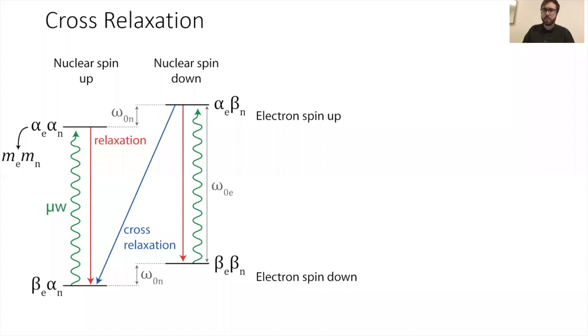All right. And then next on the list, when you mentioned that your microwave power, you don't have enough to fully reduce that Knight shift, if you extrapolate out, how much power do you think you would need to reduce it fully to zero? Yeah, want to guess at that one, Katerina? I don't think anything we can get to at these high fields, not with this setup. I mean, if we just see by how much we're changing the Knight shift right now, that's maybe less than 50 ppm. So we would need a lot more microwave power to be able to do that. It's easier at lower fields, of course. There are old papers showing that to reduce the Knight shift by at least 50%, but that's much lower field.